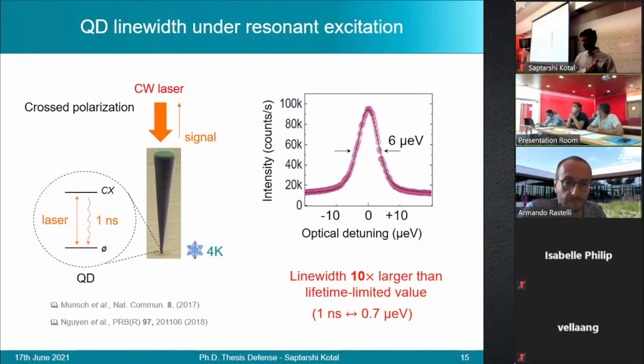So what we had done was we estimated the amount of noise. From this experiment, the 6 microelectron volts that was measured, we tried to estimate how much of this comes from the vibrational modes. Since during this measurement, they had also identified the exact position of the quantum dot that they measured, we could go back from there and estimate what the stresses that the dot would experience. And in so doing, we obtained a broadening of around 3 microelectron volts due to the vibration modes only, which means we expect the other half to be coming from charge noise predominantly.